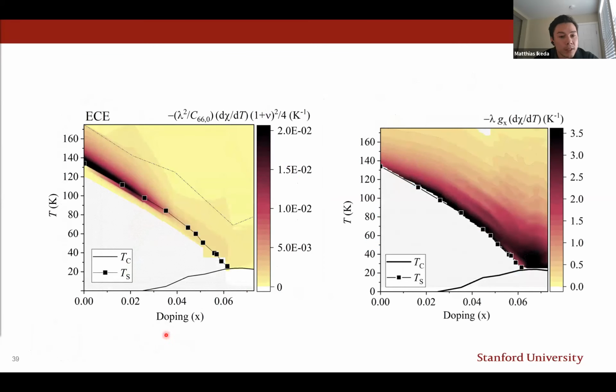Let me now come to the last slide and show the same elastocaloric effect data again in a color plot and compare it to a color plot on elastoresistivity, or in this case, actually the temperature derivative of the elastoresistivity. So this plot is something many of you will have seen before and are very familiar with. So it's very interesting to compare these two data sets and realize first that indeed the elastocaloric effect shows the largest values around the parent compound and so small dopings, whereas small values around optimally doped cobalt-doped barium 122, but the opposite is the case for elastoresistivity. As I've explained before, if we assume the temperature derivative of the nematic susceptibility to be insensitive to doping, we can now, comparing this data, extract that the nematoelastic coupling drops down by at least a factor of 5 as we approach optimally doped regions.